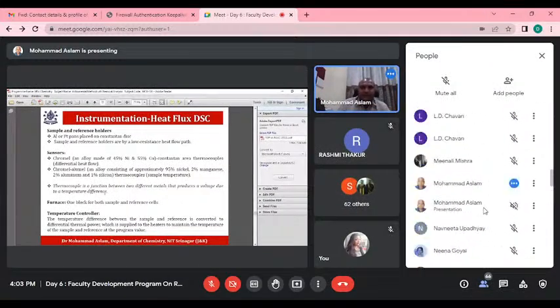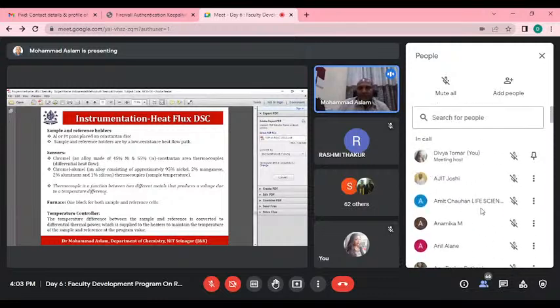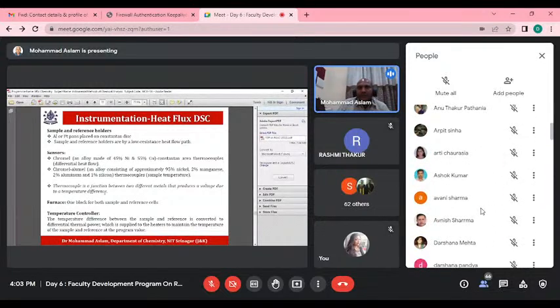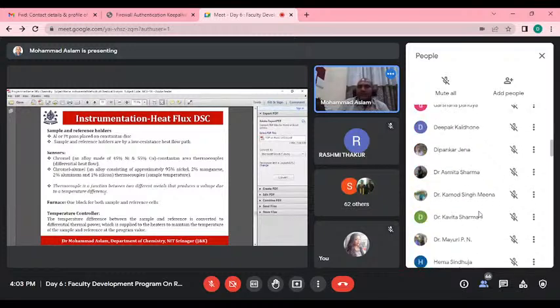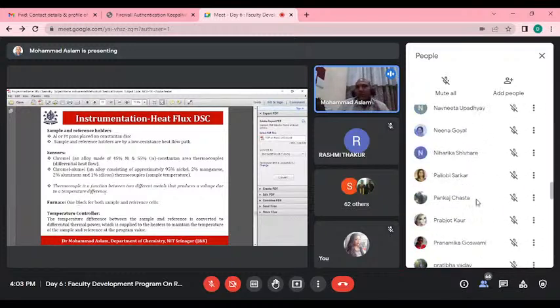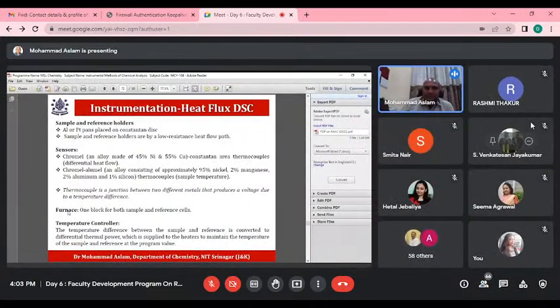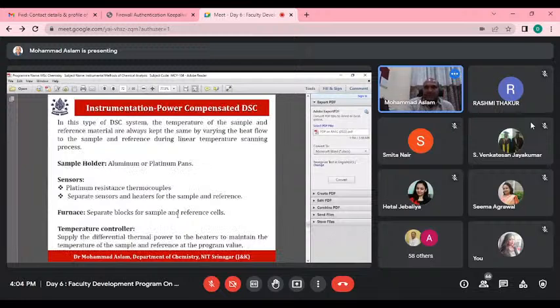is delta T. So furnace here, but it is a very important point in case of DSC, one block for both the sample and the reference. But in case of power compensated, there are two blocks for sample and reference individually. And temperature controller and the rest of the things remain similar. So here the sample holder is made of platinum pan, and sensors are mostly made of platinum thermocouples, of platinum metals.